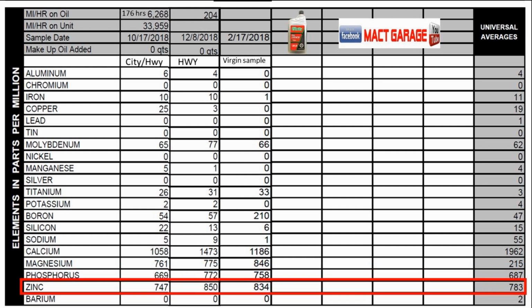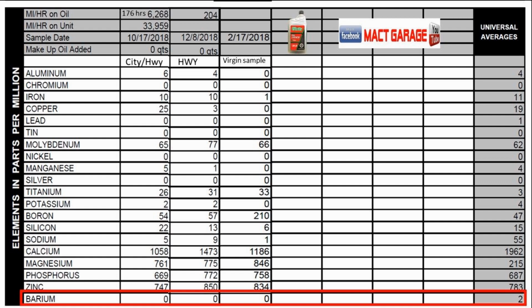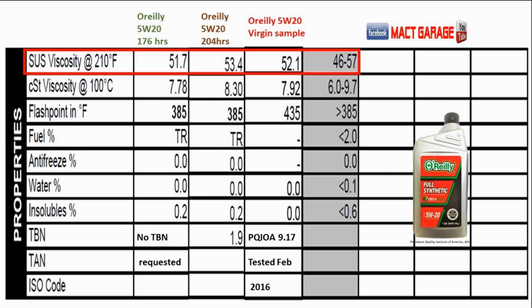Zinc. Zinc is the go-to for a lot of oils, and they add it in there. And as we can see, the virgin sample of the O'Reilly started out at 834, and then my Edge, the 204 hour running, came in at 850, which again is higher, and again is the leaching. But as we look at it, the 176 hour Edge came in at 747. So again, we can say that the zinc was getting used up as the oil was being run through the engine. The universal average, of course, is 783 for used samples. And there is no barium across the board in any one of the oils, with the universal average being just 2 parts per million.